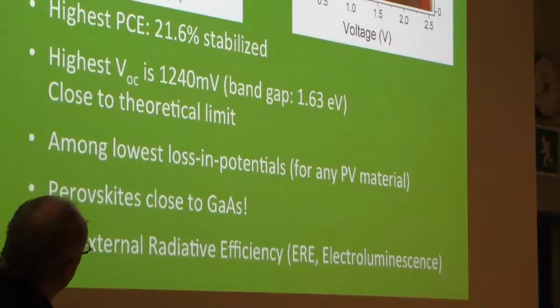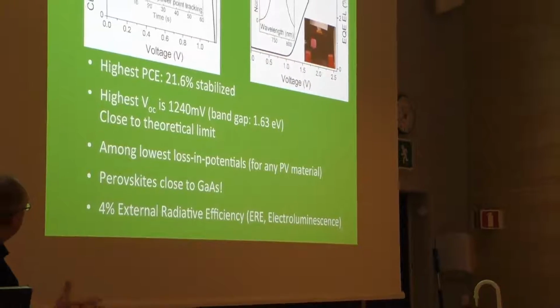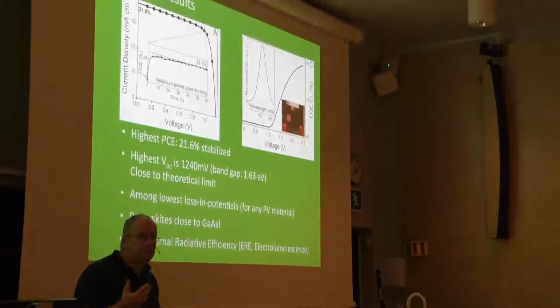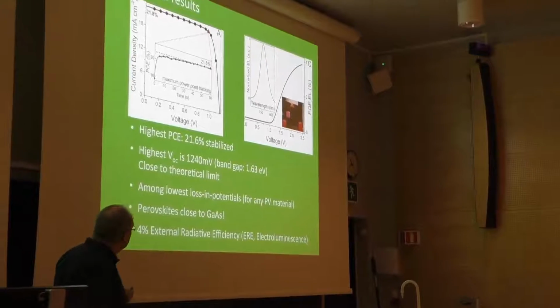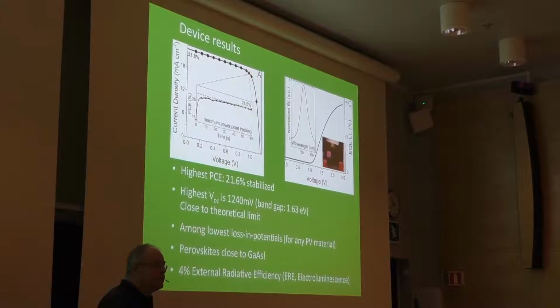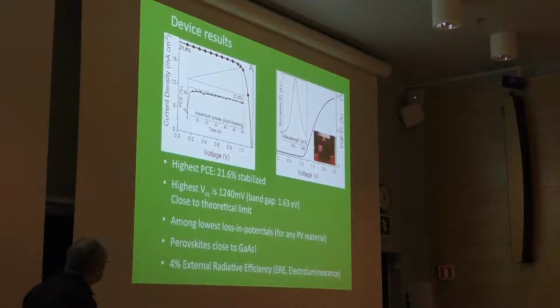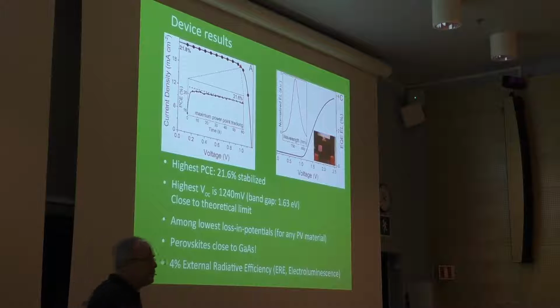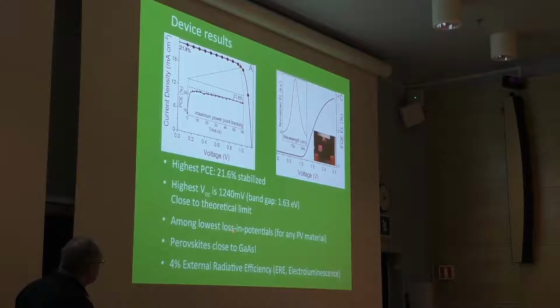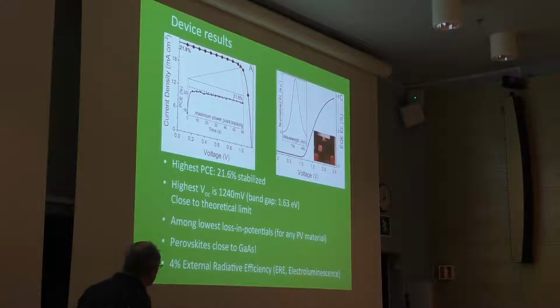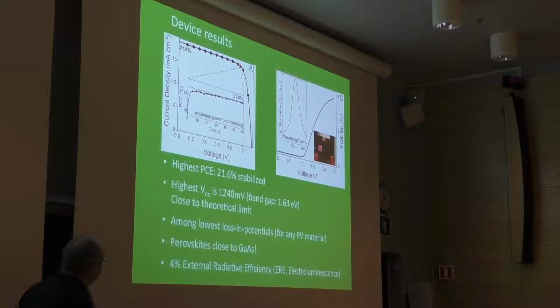This is very interesting, I'll come back to that. It's a very high voltage, 1.24 volt at maximum. The band gap is 1.63, and it's the theoretical highest voltage we can have is about 1.33 volt. You always have to get rid of about 0.3 electron volt from the solar spectrum because of entropic losses in the sunlight. So the highest theoretical VOC we can get is 1.33. We're only 90-100 millivolts away from that. It means that it's a very, very high quality semiconductor. So it's among the lowest loss-in potentials for any kind of PV material. I think it's just gallium arsenide which is better. And we have now an even higher 4% electroluminescence yield at best, 1% if we have solar cell conditions.